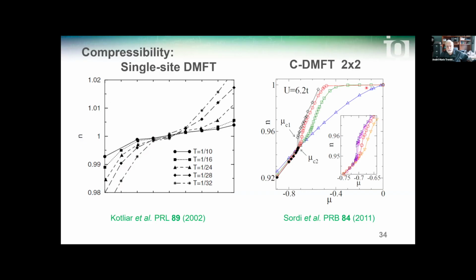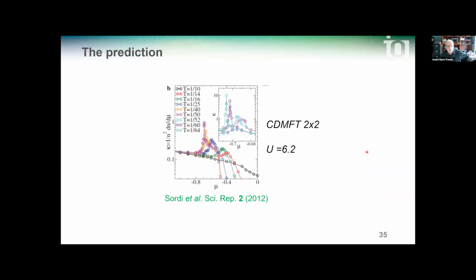Going to cluster dynamical mean field theory, the effect of super exchange J can be felt. The first order transition that was here between insulator and metal is moved to finite doping. So it's between two metals. One is a pseudogap, the other one is an ordinary metal. You can also see an infinite slope of the derivative, or of the compressibility, at the temperature of the critical endpoint. So as we move to a critical point by raising temperature.